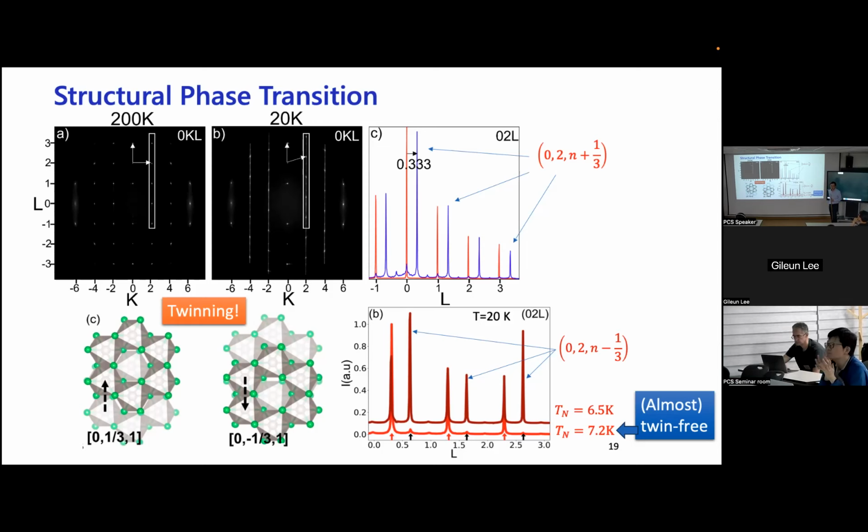So, thinking about the interlayer coupling as a magnon dispersion, that's really the most direct way of measuring the coupling strength: measuring the magnon dispersion relation along all directions, and along the Z direction you have to measure the magnon dispersion. To measure dispersion you have to measure more than one Q point, right? Raman will be just a Q equals 0 point, so that will be difficult. Having said that, it's not the only way to determine the dispersion relation, but coming from a neutron scattering background, that's how I would determine it.